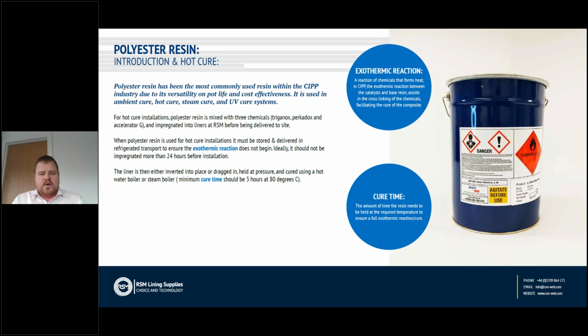The liner can be dragged or inverted into place. It is suitable in most applications to go around bends, and it is also suitable in most applications to form a fully structural pipe within a pipe capable of withstanding ground loading. Hot cure applications remain the most flexible of liner installations. Little risk during the installation, and also suitable for most diameters, most pipe shapes, most pipe sizes. And the resin will not prematurely cure. The cure is only accelerated by the addition of heat, which kicks off the exothermic reaction, cross-linking the chemicals and forming the basis of the composite, the pipe within the pipe.